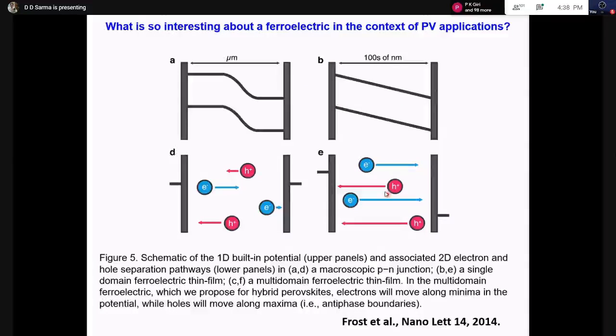And that's why you can see these big, long arrows suggesting that if you had a ferroelectric material, then the photovoltaic effect would actually be aided by this tremendous internal potential. And that's the reason there's a whole school, a whole network of activities where people are trying to make photovoltaic materials out of ferroelectric material. Unfortunately, for most of the ferroelectric materials, the band gap is very large. And as I told you, the band gap has to be optimum. So the ferroelectric materials have not proven to be good photovoltaic materials.